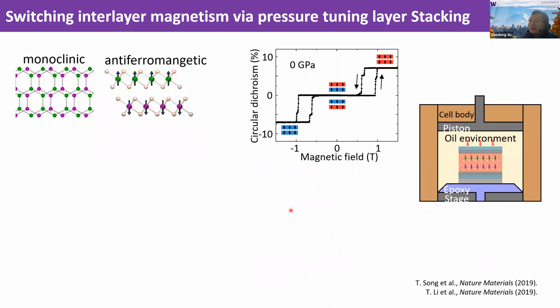Now, the question is, can we actually control the layer stacking and the interlayer coupling? A few years ago, we used a hydrostatic pressure technique to control the interlayer coupling. For example, we started with a bilayer of chromium triiodide, initially with monoclinic stacking and antiferromagnetic.